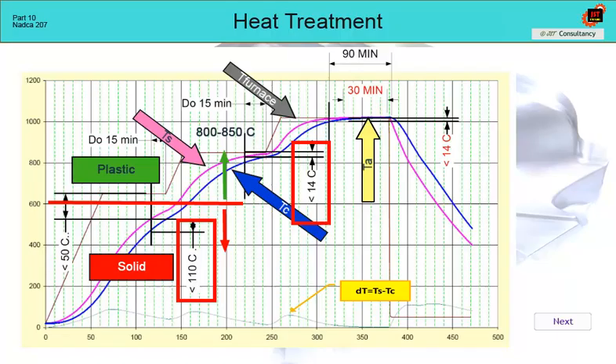The soaking time at the austenitizing temperature should be a maximum of 30 minutes from the moment when the hardened part reached the austenitizing temperature at Ts, and at the same time the difference between Ts and Tc will be less than 14 Celsius, or a maximum of 90 minutes from the moment when the austenitizing temperature was reached by the first of the thermocouples, usually T-surface.